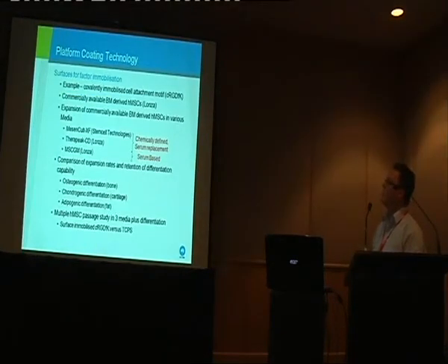This is a study that's almost finished. We're taking our RGD surfaces, and we're using commercially available bone marrow derived mesenchymal stem cells. We're expanding those in various media, and we're using three in this case: two chemically defined serum replacement medias, and a serum-based standard growth media for MSCs. We're comparing expansion rates and retention of differentiation capacity through the three lineages, as you've seen earlier, doing multiple passages in three media plus differentiation, our synthetic surface versus TCPS, and looking at markers.